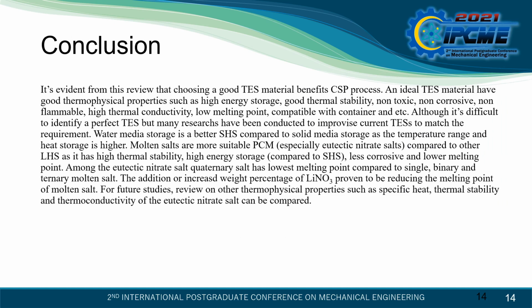As a conclusion, it's evident from this review that choosing a good thermal energy storage material benefits CSP processes. An ideal TES material has good thermophysical properties such as high energy storage, good thermal stability, non-toxic, non-corrosive, non-flammable, high thermal conductivity, low melting point, compatibility with the container, and so on. Although it's difficult to identify a perfect TES, many studies have been conducted to improve current TES to match the requirements. Water media storage is better as sensible heat storage compared to solid media, as the temperature range and heat storage are higher.